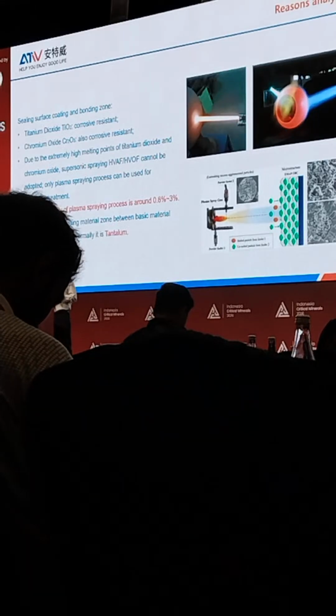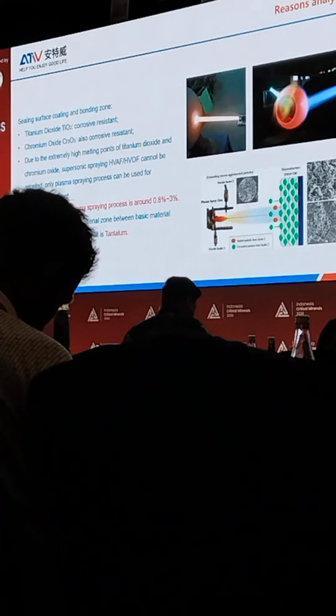So normal HVOF supersonic process cannot be used. Only the plasma coating process can be used in this area. But the plasma process has a big problem because the porosity of the coating is very high, sometimes from 0.8 to maybe 3 percent. Also, as you know, the basic material titanium is very light and very soft, but the coating is very hard. So between the hard coating and the soft basic material, we have to find a bonding zone to connect the hard coating and the soft basic material.